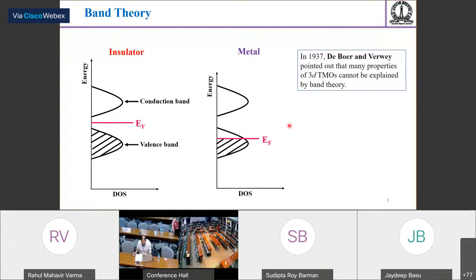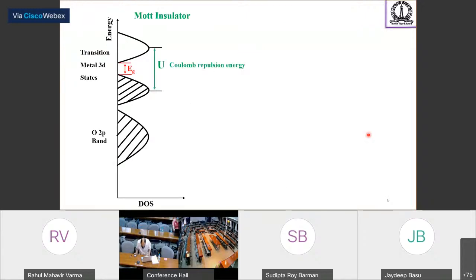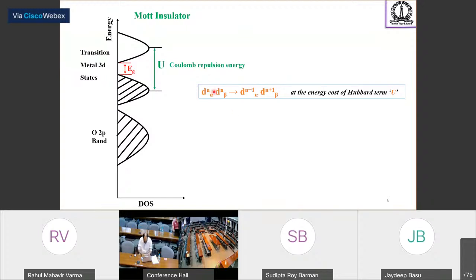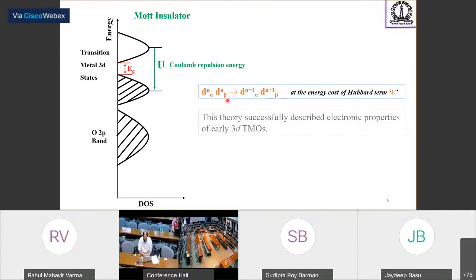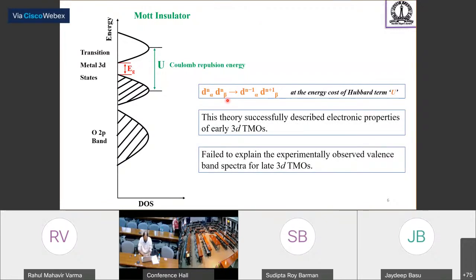Although this theory was successful in many respects, it fails to explain many properties of 3d transition metal oxides, which was pointed out by de Boer and Verwey. Indeed, this theory suggests that all 3d transition metal oxides should be metallic in nature, but in reality most of them are either insulators or show a metal to insulator transition. To solve this disagreement, Mott, and later on Hubbard, introduced the on-site Coulomb interaction term U, and proposed a charge fluctuation of this type, where n is the number of electrons and alpha and beta are two different transition metal sites. Although the introduction of such a Coulomb interaction term successfully explained the electronic structure of early transition metal oxides, this theory fails to capture the experimentally observed valence band spectra for late transition metal oxides.